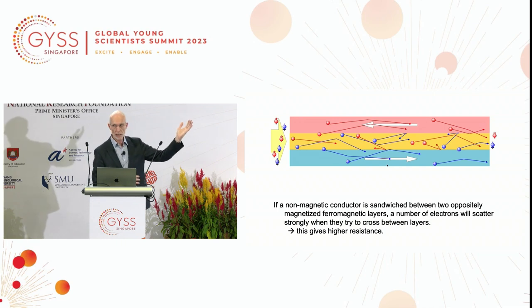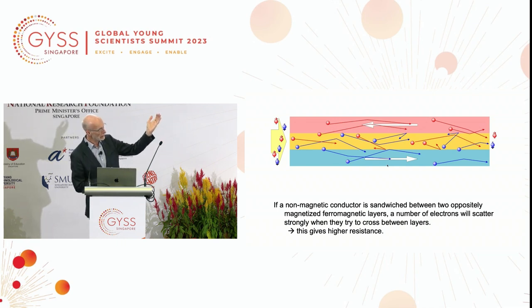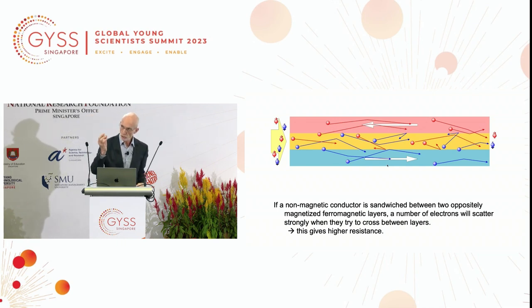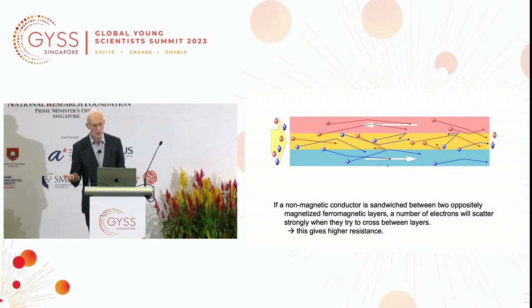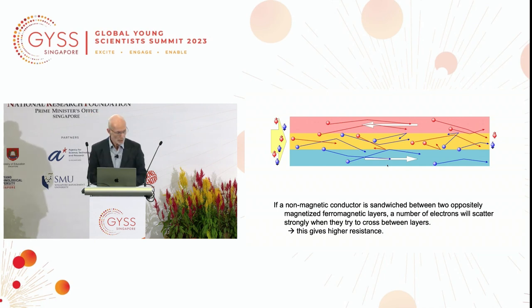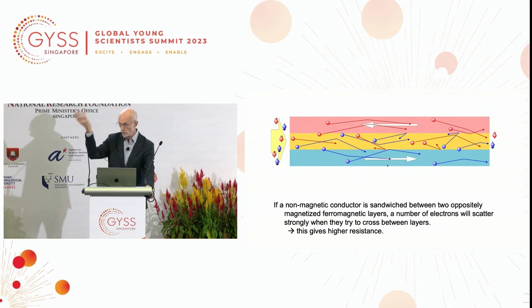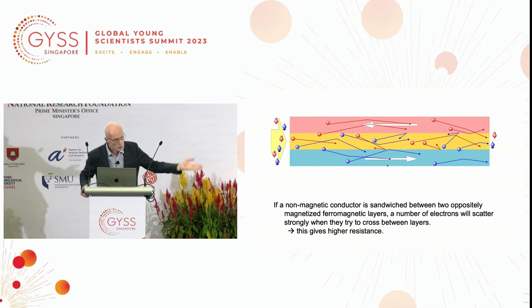Now let's see what happens if we take a sandwich. The red layer has a magnetization pointing to the left, the blue layer to the right, and in between we have a thin layer of copper. Each of these layers is atomically thin, let's say a few atomic layers thick. We can make these materials by simple sputtering techniques, which I'm not going to discuss. If you introduce a current into this material from the battery, then the red layer prefers the red electrons, spin down, and the blue layer, the blue electrons.